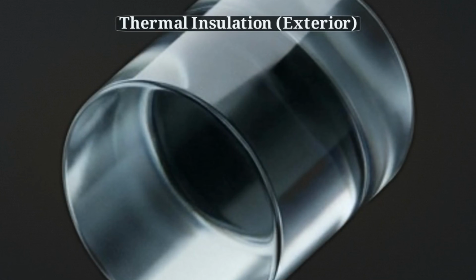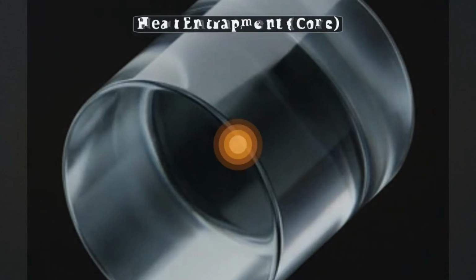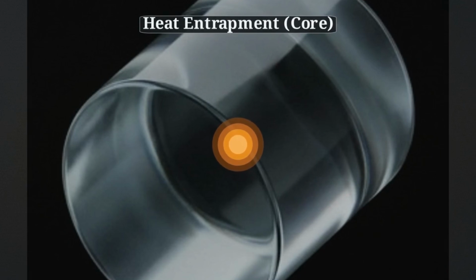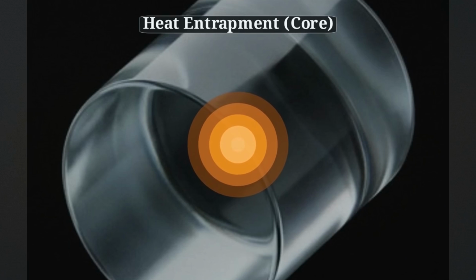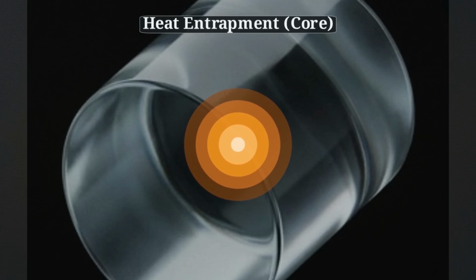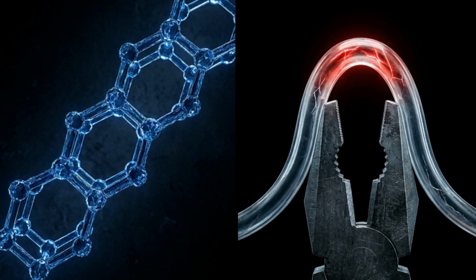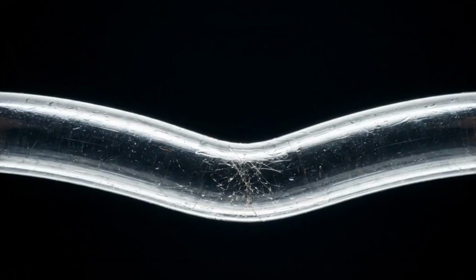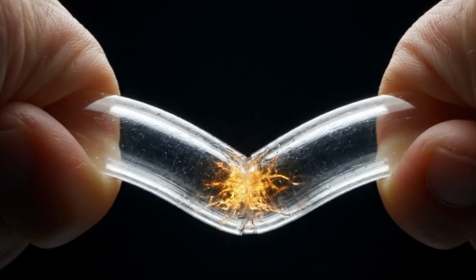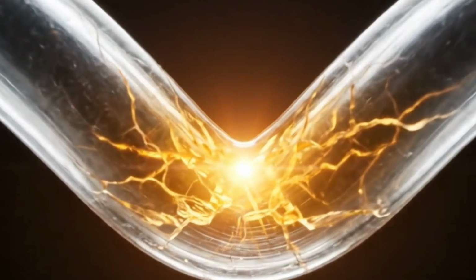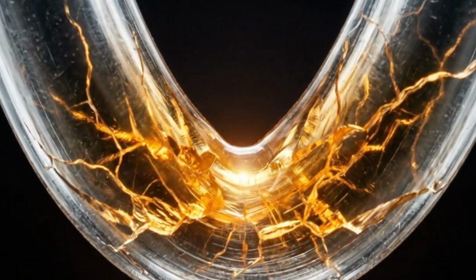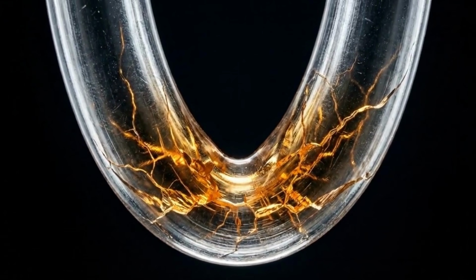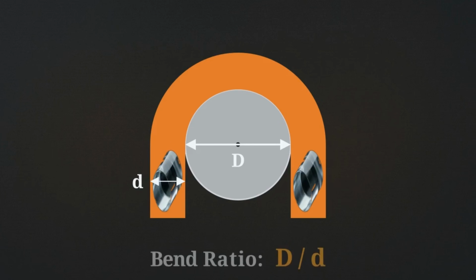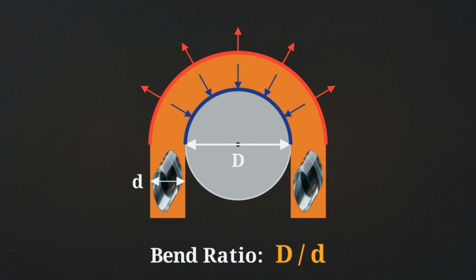However, PVDF is also very rigid and acts as a thermal insulator. Because it has extremely low thermal conductivity, it cannot easily dissipate heat into the surrounding environment. This creates a direct conflict between the material's properties and its application. The mechanical action required to use this rigid line, bending and cinching it, triggers a reaction that can compromise its own molecular architecture. In rigging, the severity of a bend is measured by the D/d ratio.